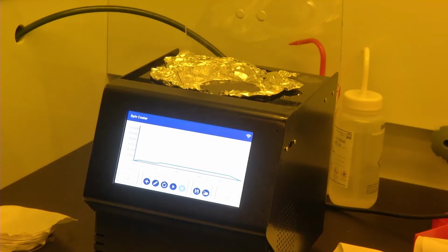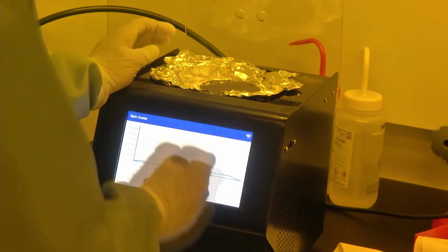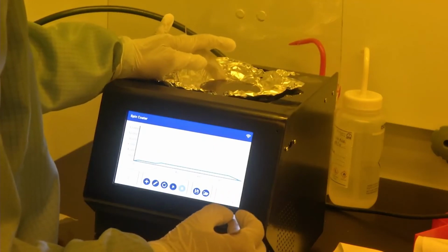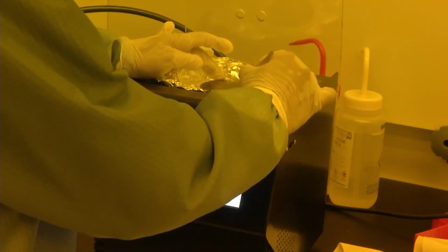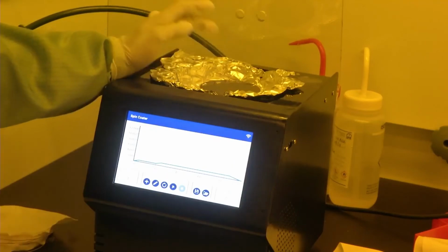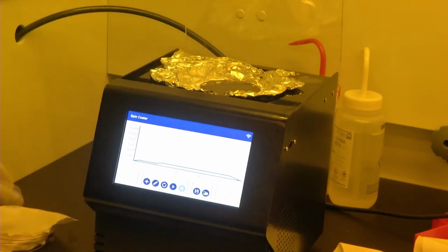Now before spin coating, it's always good to check by gently moving the silicon wafer using tweezers, not moving very fast, just to see if the silicon wafer is moving on the chuck or not. This is to ensure that once we start the spin coating, the wafer does not break because of loss of vacuum. This check needs to be done very carefully, with very slight force, just a touch, to ensure that it is nicely holding it. Now we have checked it and we are ready for spin coating.